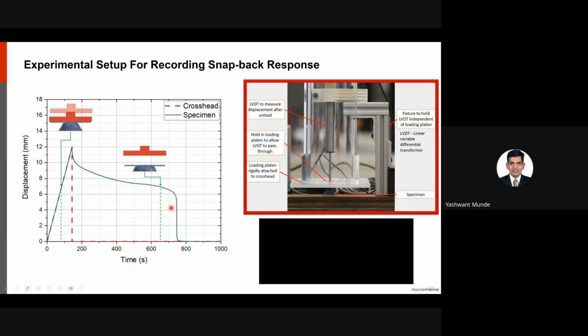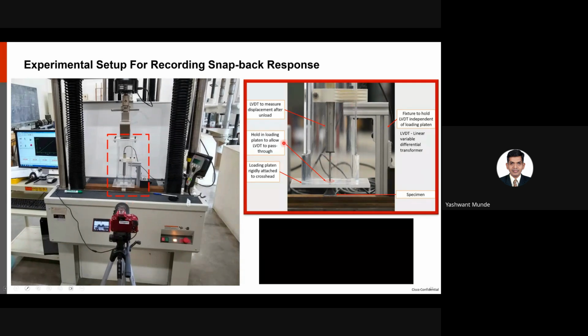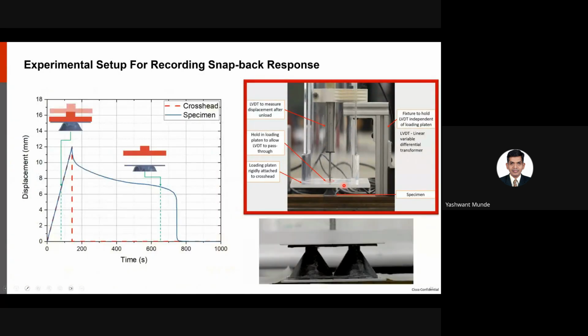So for that, we designed this fixture, which is expanded here. Basically, it's made of a flat platen here with a hole and an LVDT attached. So the loading from the test frame is acting on this flat platen, which is compressing the core or it's compressing the unit cell. And the LVDT is always in contact with the top face of that unit cell. And upon unloading, as you can see again here, the LVDT is still in contact with the top face of the unit cell, thereby recording the entire displacement time response. So we use this to validate some of our simulation of this snapback behavior.